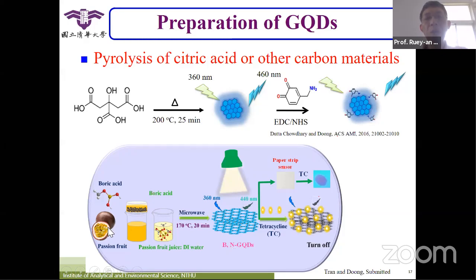And for those natural products, most of them contain nitrogen. So when you use natural products to fabricate your graphene quantum dots, you can always get nitrogen-doped ones. Since you have the nitrogen doping, their electron density will enhance dramatically. So their quantum efficiency will be good, and their electrochemical conductivity will be good. So we can use this for paper strip sensors to detect tetracycline or some other compounds, and also we can decompose them. So that is quite simple.